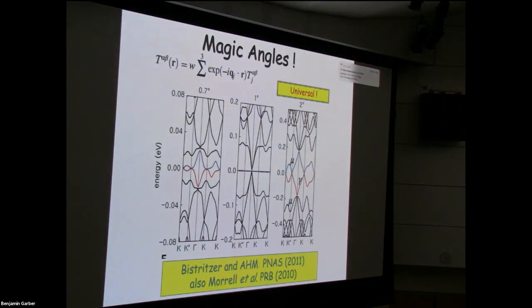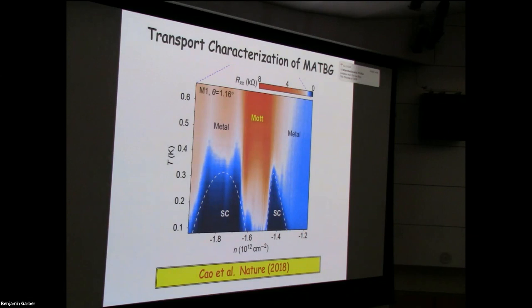So you have an isolated flat band containing 4 electrons per Moiré period with practically no electron velocity, and we know when that happens, all of the physics is going to be dominated by electron-electron interactions between electrons that are constrained to lie in this Hilbert space, very much like Landau-level physics. And this is actually the system in which Pablo Jarillo-Herrero made the observation I showed you before.